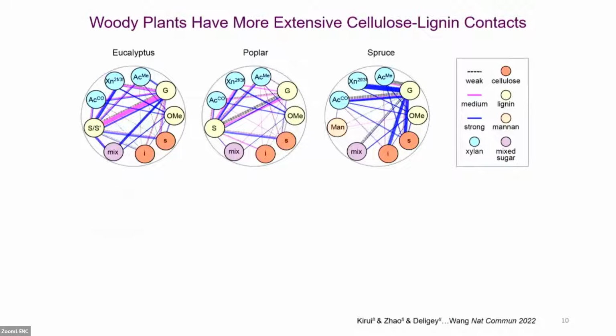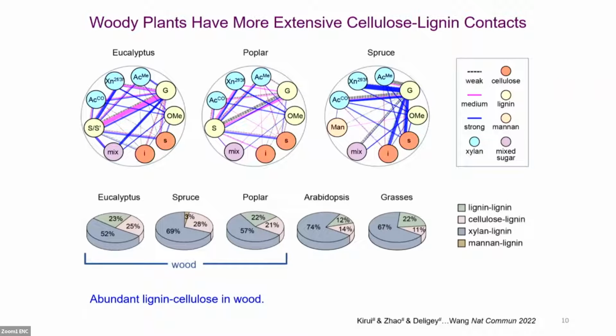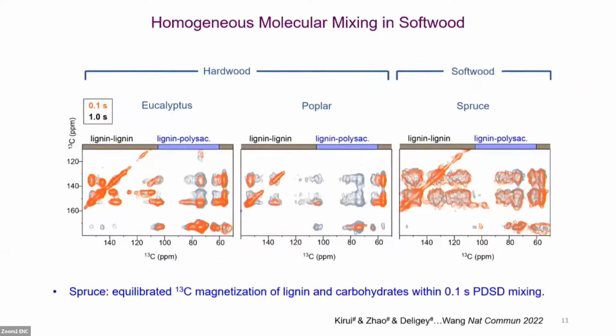Now we can summarize the interactions into this figure, and we use the blue bold lines to represent the strong interactions, and the pink and the black ones as the medium and weak interactions. They give us the basic information about the interactions. The result shows that in the wood samples, we have more abundant lignin to cellulose interactions when compared to grass or Arabidopsis. Now we can give a zoomed-out view of our PDSD spectrum. We can notice the softwood one looks special. The short-range 0.1 second mixing time spectrum can match the long-range spectrum very well. That means there must be homogeneous molecular mixing in the softwood, but it doesn't happen in the hardwood.